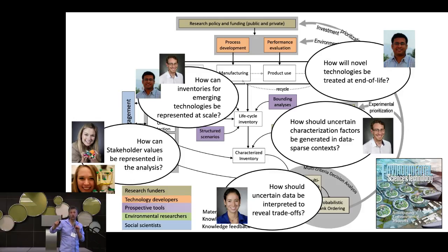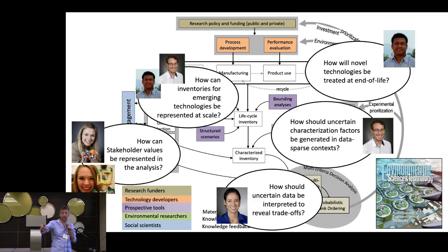What I didn't show is, what are the thermodynamic limits that should constrain our imagination? There are thermodynamic limits to performance on the use phase. When are we going to go to multi-junction cells, for example, to try and push the upper limit? There are thermodynamic limits on the manufacturing phase. There's only so much atomic efficiency that we could possibly get. And the sense that I'm getting, and I'm really excited about what Ryan was saying about 1366, is that we're reaching the asymptote on the manufacturing phase for monocrystalline silicon with the paradigm that we've been using, building out a single crystal and cutting it up as thin as we possibly can.